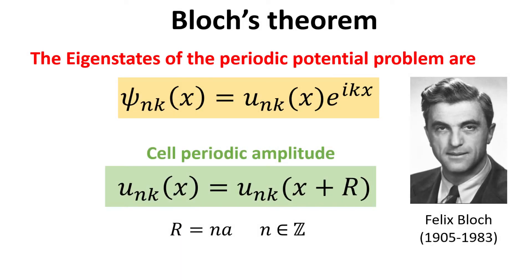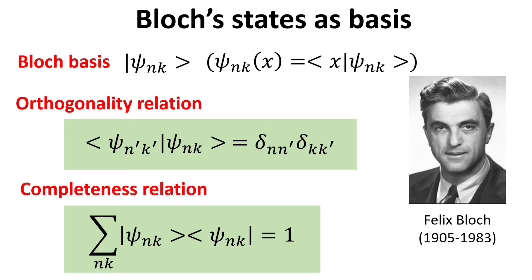The amplitude function has an extra important feature: it is a periodic function with the same periodicity of the lattice, as stated in the green box. This function is commonly called the cell-periodic part of the eigenstate. The full eigenstate, shown in the yellow box, is often called a Bloch state, after Felix Bloch who derived this important result in his thesis. As eigenstates of the Schrödinger equation, the Bloch states form a complete basis set to expand the full wave function of electrons in a crystal. In ket notation, the orthogonality and completeness relations of Bloch states are highlighted in green boxes.